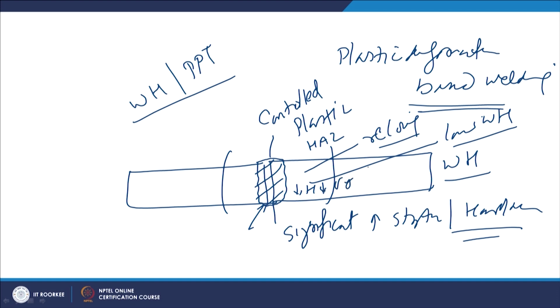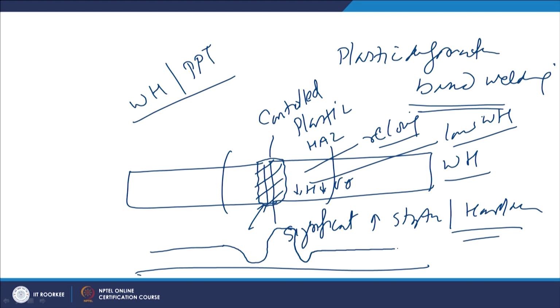So, the typical pattern of hardness variation observed in this case is that in the base metal hardness is high, but as we approach the heat affected zone hardness is reduced, and as soon as we reach the weld zone hardness is increased again. This increase in hardness in the weld zone is attributed to the plastic deformation and related work hardening effect, while in the heat affected zone next to the weld metal, the softening or reduction in hardness occurs primarily due to the recovery and loss of the dislocations, which takes place due to the heat generated during the plastic deformation based welding processes.